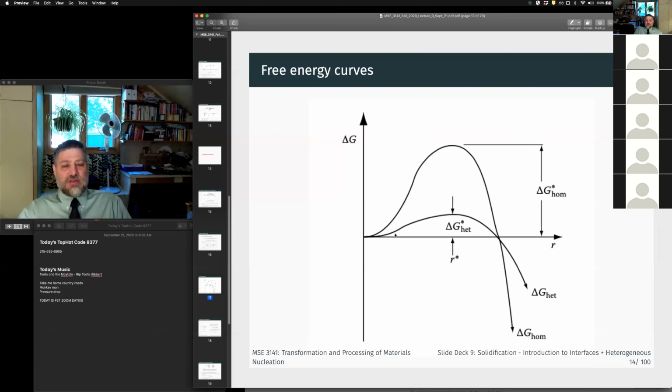And so that's by moving this surface energy term, this volume term down. That's why this curve ends up having a slightly different shape, because you need a smaller volume of material for the same critical radius, right? And so that's why it just doesn't follow the same exact trajectory over here, because your surface energy is different, and the volume that you need is different as well, right?